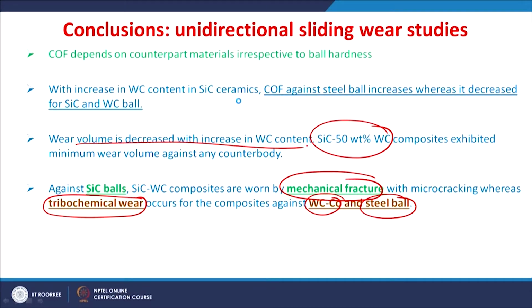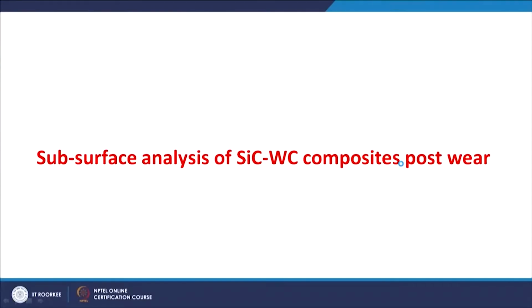Amongst the three counterbodies, when we use the silicon carbide counterbody, purely mechanical fracture is dominating. So, it is very important to understand the origin of such a mechanical fracture. So, we selected these silicon carbide tungsten carbide composites worn against silicon carbide ball only, where there is a purely dominantly mechanical fracture, for further studies of the subsurface analysis. The subsurface analysis study is very important to identify the origin of such a fracture. So, we purposefully have not taken these silicon carbide tungsten carbide composites sliding wear studies against the tungsten carbide and steel ball, where there was a type of tribochemistry.